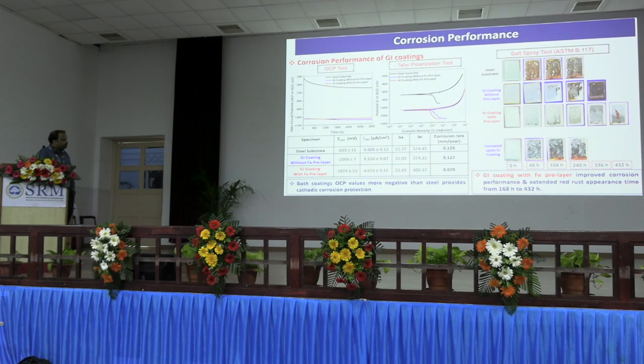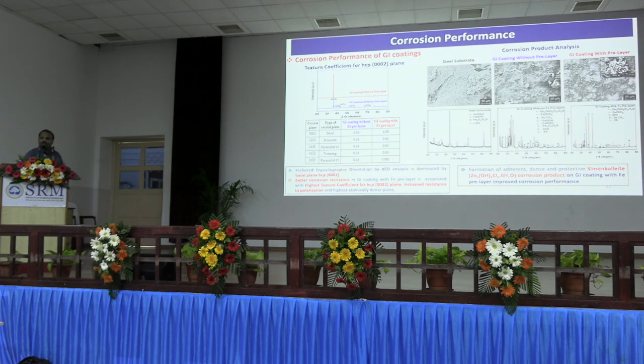And when we conducted the salt spray test, it extended the corrosion life from 168 hours to 432 hours. So this is an interesting improvement in the corrosion resistance of the modified galvanizing coating. It is mainly due to the formation of spangles, or overlay spangles, on the coating with the highest HCP texture coefficient, which actually increases the polarization resistance.